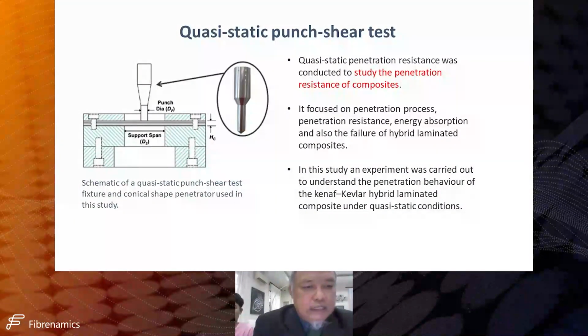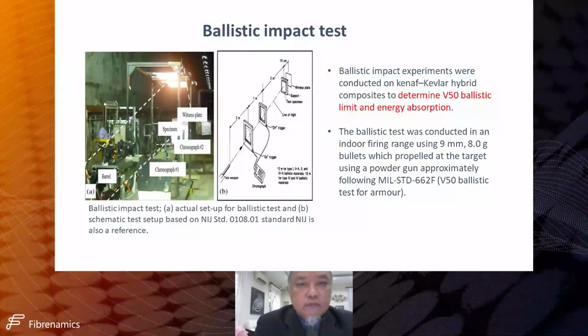And on the left-hand side is a schematic of the quasi-static punch shear test, fixtures and conical shape penetrator used in this study. And also, one of the important tests that we carried out is the ballistic impact test. Ballistic impact experiment we conducted on this material, Kenaf and Kevlar hybrids, to determine the ballistic limit and energy absorption. So we have the facilities at our lab in our university, so we carried out that test.